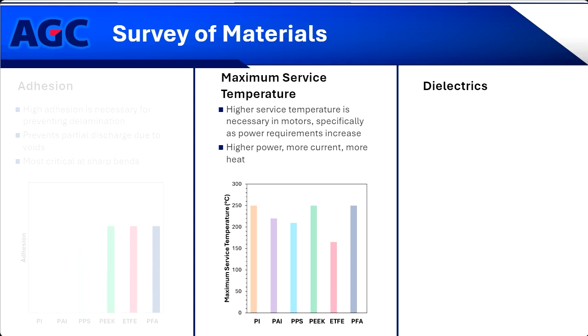You can see the one material that I've really highlighted here so far is ETFE, and it doesn't perform quite as well as the rest of the materials. But as I mentioned with adhesion, through some polymer modification, we are able to increase that maximum service temperature of the ETFE to be equivalent to your PPS and close to some of your polyamides.